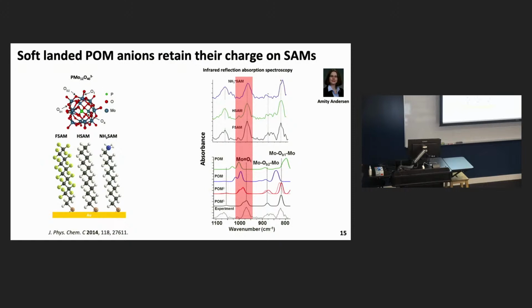Before I get into that, one thing that bears mentioning is that these clusters are inherently 3- species. When we deposit them on these self-assembled monolayers, we find from infrared spectroscopy that they actually retain their 3- charge on the surface. Well, how do we know that? We can calculate the vibrational modes of these clusters using density functional theory. In particular, the metal-oxygen terminal bands, which are this one here, have a characteristic vibration at this wave number, which shifts dramatically towards higher wave number as the charge of the cluster decreases. That's what we calculated. On the surface, though, when we make the measurement, we find that those bands are not shifted. They stay essentially in the same place. So this is pretty good evidence that these clusters remain as 3- species on the surface.